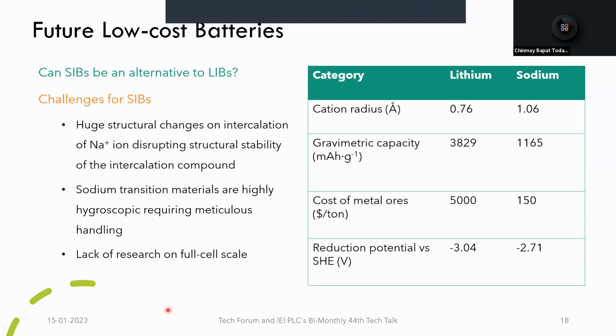Can sodium-ion batteries be an alternative to lithium-ion batteries? Well, I think yes, only if these challenges are resolved. First and foremost, sodium cations have a larger cation radius than that of lithium, and therefore the expansion and contraction that we saw before due to lithium intercalation can be exaggerated when we use sodium, which can disrupt the structural stability of the intercalation compound. So that challenge has to be solved.